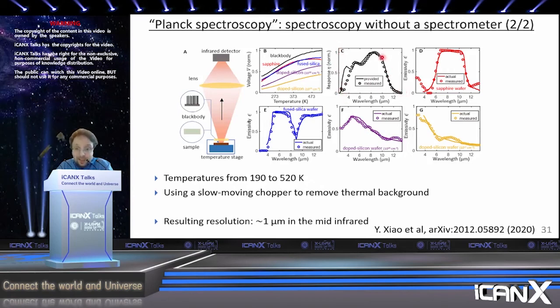You can see the dots over here, the circles, is what we end up measuring and extracting. The solid line, which we call provided, is really just the spec of the detector. So we take the detector spec, what the detector responsivity should be versus the wavelength, and multiply it by the transmission spectrum of the lens, and that's what this provided spectrum is. Already you can see that we can measure the spectral responsivity of the detector without using any conventional spectrometer, prisms, gratings, and so forth.